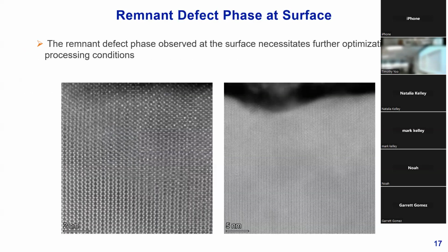However, when we get closer to the surface, we can see that about 10 to 50 nanometers below the surface, throughout the entire film, we consistently see some of this remnant gamma phase, as well as that unique defect structure that again was due to anti-phase boundaries. And so this necessitates further optimization of processing conditions. This is rather important to note because when you think about forming electrical devices, that interface structure has to be really pristine in order to form nice contacts, either with junctions or with metal contacts and such. And so we really need to be able to resolve these types of defects, especially at the surface, if you want to get the most out of this type of material.